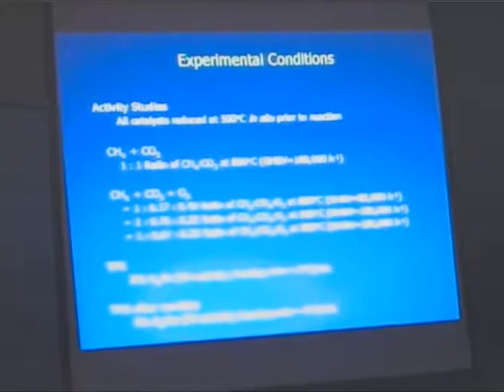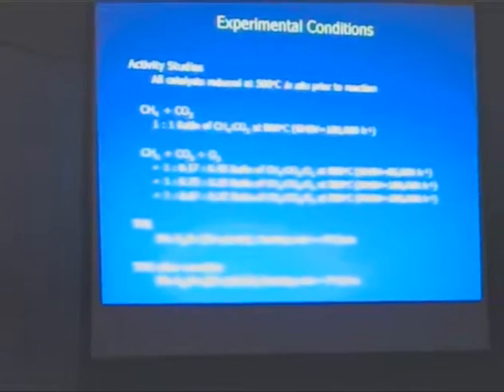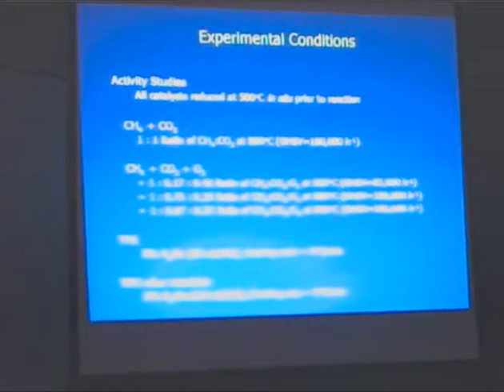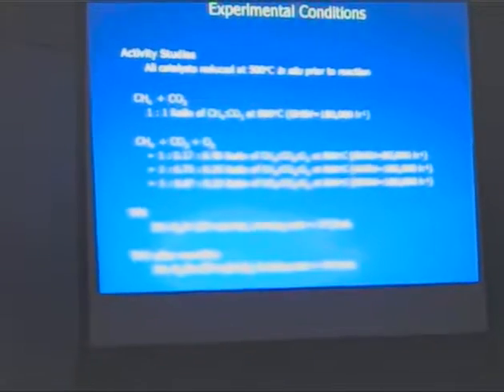The last two that we looked at were primarily for our own interest because we are trying to look at using oxygen permeable membranes, and rather than using those membranes where oxygen is a primary component, like for partial oxidation reactions, we're interested in looking at these dense oxygen permeable membranes to bring or bleed oxygen in as a supplement for a reaction in which carbon deposition occurs. What we're interested in doing then is to see what happens if we have a dry reforming ratio, a 1-to-1 ratio, or close to a 1-to-1 ratio, with then some oxygen being added in. And these are the first two ratios of the study that we've been doing.